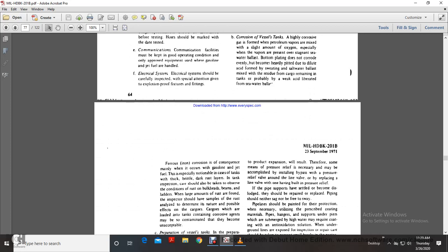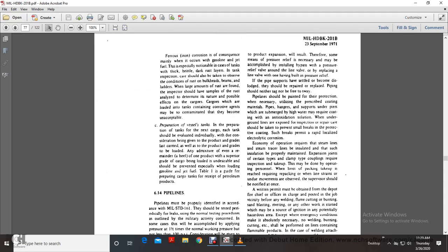Alright, ferrous iron corrosion is consequently mainly associated with gasoline and jet fuel, especially noticeable in the case of tanks with a thick and brittle dark rust layer. During tank inspection, care should be taken to observe the condition of the rust on the bulkhead and beam. If a large amount of rust is found, inspectors should take samples of the rust and analyze them to determine its nature and the possible effect on the cargo. If cargoes loaded into the tank become contaminated by corrosive agents, they become unacceptable.